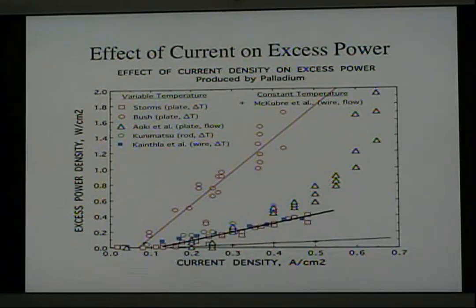Here's another example of this effect that compares a variety of samples. Well, first of all, notice that none of the samples show excess energy unless a critical current is applied. But once it's applied, the excess energy now rises at different rates. Well, this is caused because these samples have different areas, different shapes, and different amounts of the nuclear active material on their surface. But nevertheless, regardless of these conditions, this critical onset is always seen.